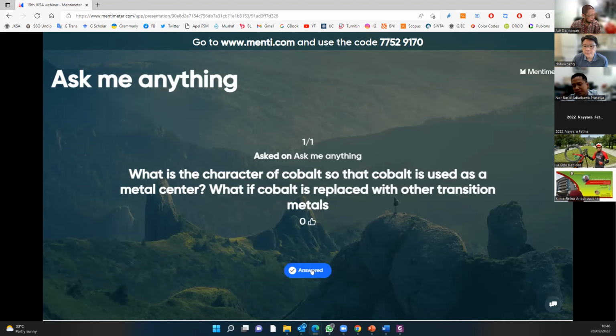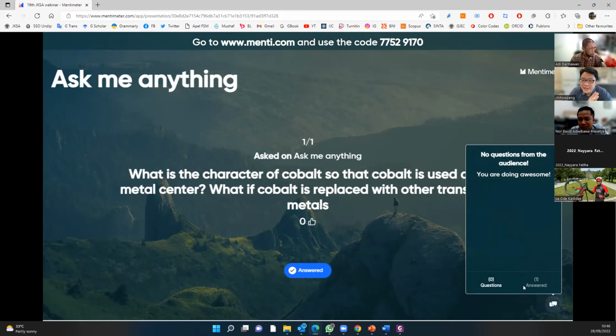And I have one question, Professor. So you said that the ligand is more important rather than the cobalt as the metal center. Is there any special requirement for the type of the ligand that can be used better rather than the other ligands? Actually, we tried a lot of organic compounds. It's like a screening, okay? And we only found tropone. And by the theoretical calculation, we hope to understand why the 7-member ring is that important. Because it provides the resonance structure, but we are still calculating it because the simulation is not our expertise. So it spent a lot of time, and we are still learning that.